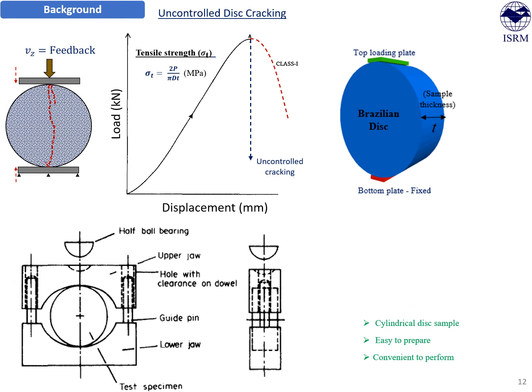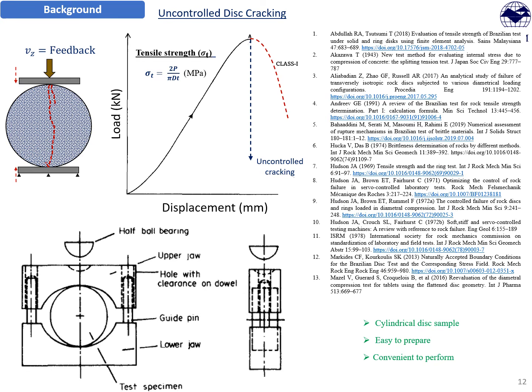Now, the Brazilian disc test. You can see it's a simple experiment. In this experiment, we take a disc shape specimen and we compress it diametrically and record the load versus displacement response. And we capture the peak load at which the specimen cracks. Now that peak load P is linked with the tensile strength of the material. Simple experiment and easy to perform. Now the issue was, first, the reliability of the tensile strength test. In the literature, it was established that if the crack initiates at the center of the disc specimen, then the corresponding peak load will provide a reliable estimation of tensile strength.